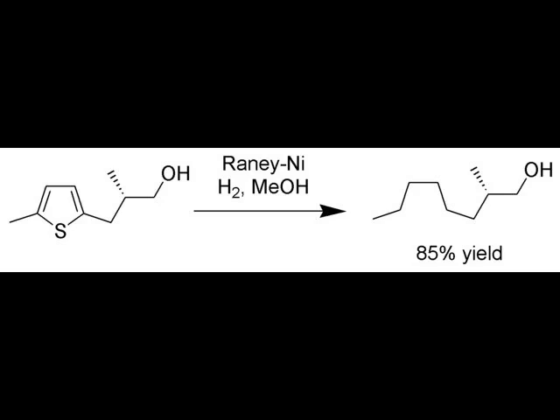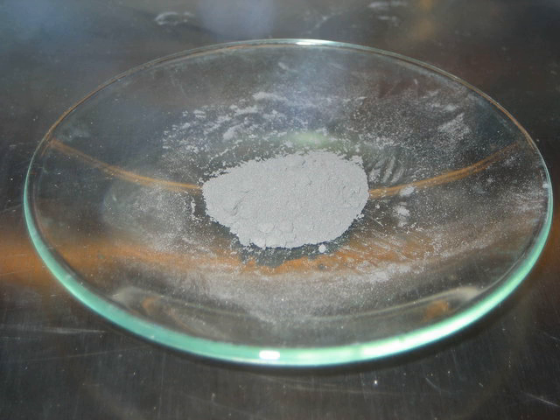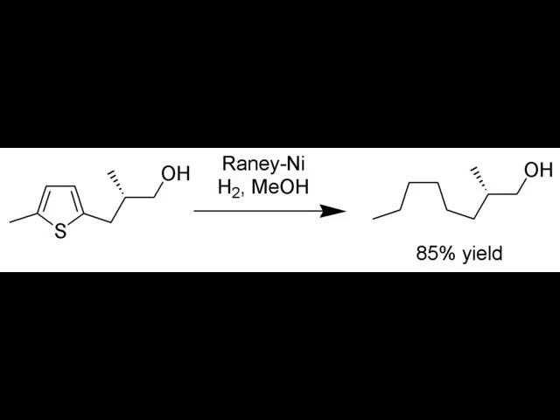The most common starting alloy in industry contains an equal amount per weight of nickel and aluminum — incidentally, the same ratio Murray Raney used in his discovery of Raney Nickel. During the quenching procedure, small amounts of a third metal, such as zinc or chromium, may be added. This is done to enhance catalytic activity, and as such, this third metal is called a promoter. Note that the addition of a promoter changes the alloy and its resultant phase diagram to that of a ternary alloy, leading to different quenching and leaching properties during activation.